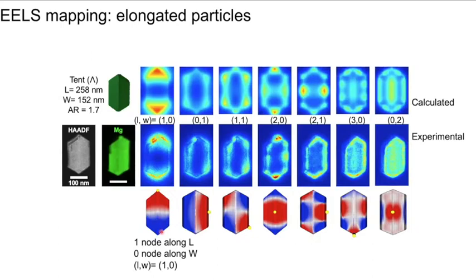It turns out that your dipole is now non-degenerate. So there's going to be a longitudinal dipole and a transverse dipole. I'm going to use this notation LW, saying, for instance, here there is one node along the length and zero nodes along the width. So this would be my 1-0 mode. This would be the 0-1 mode, and then the quadrupole 1-1, and so on. We've been able to map those both in numerics and in experiment, and understand how the modes behave when we are elongating these particles.